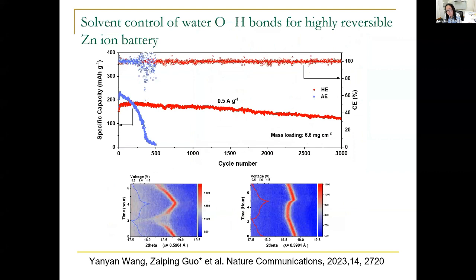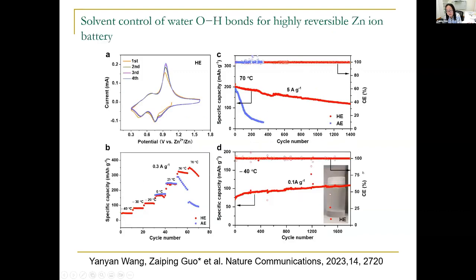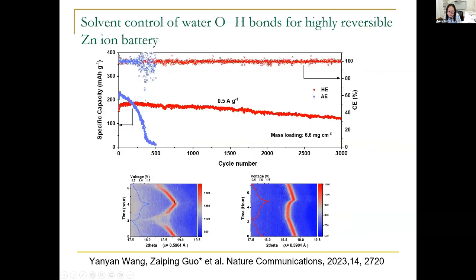Then we coupled the zinc with vanadium pentoxide to construct a full cell and tested the full cell battery performance. Here I would like to mention the mass loading for the cathode is quite high, 6.6 milligrams per centimeter square. The cell can be charged and discharged for 3,000 cycles, with capacity retention of about 80%.